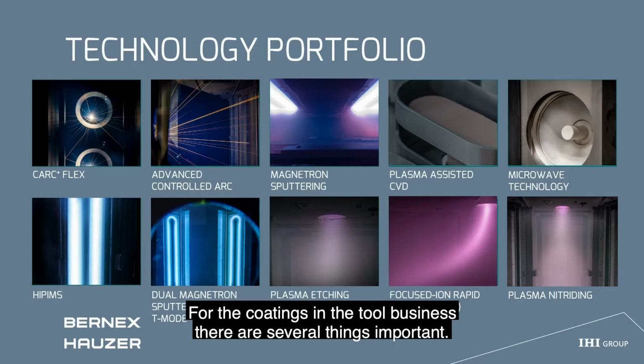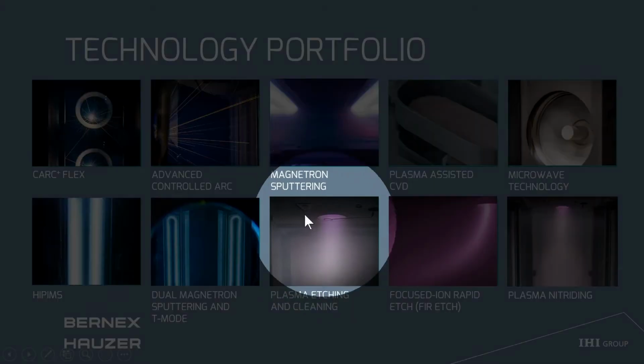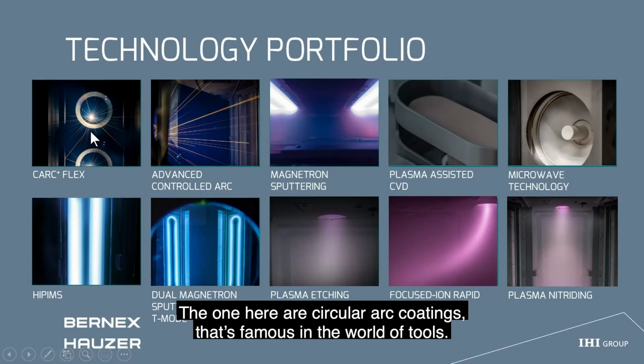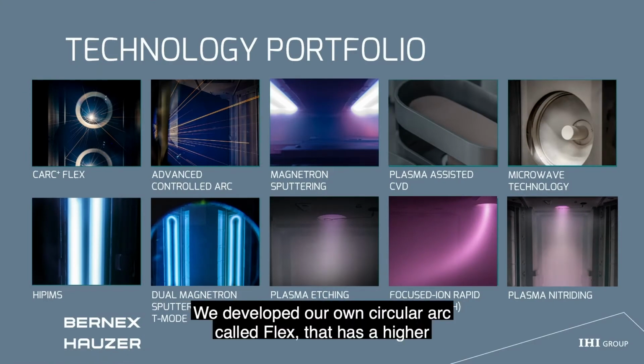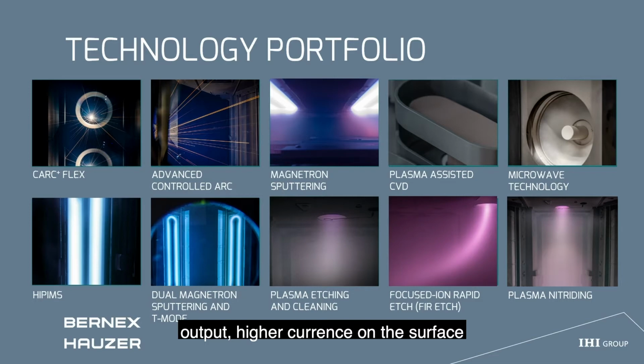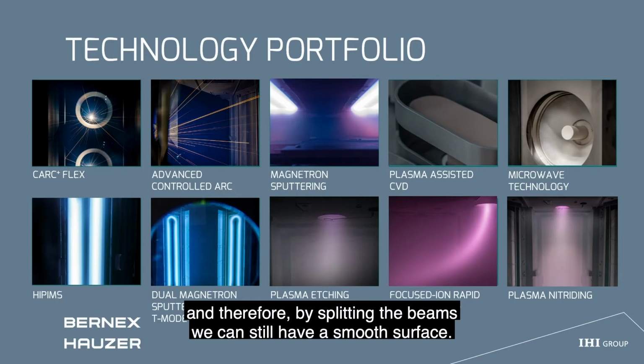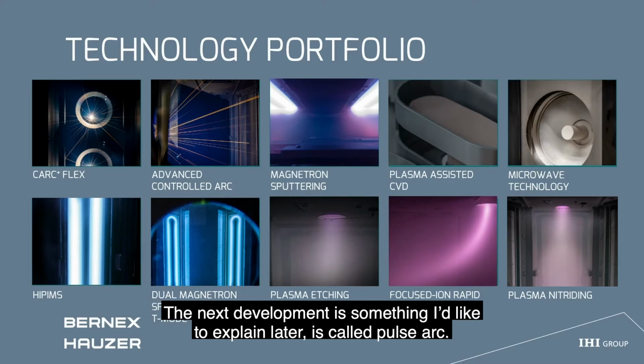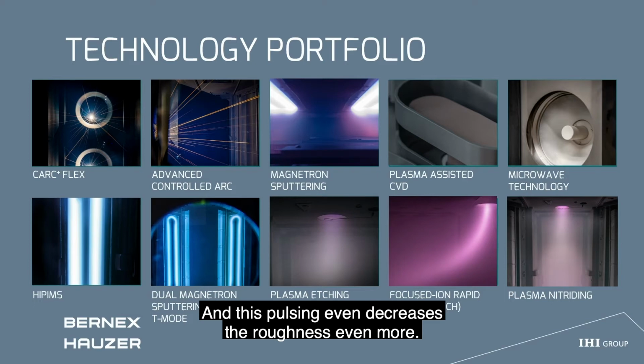For the coatings in the tool business, there are several things which are important. The one here is circular arc coatings. That's famous in the world of the tools. We developed our own circular arc called Flex. So we have higher output, higher currents on the surface, and therefore with splitting the beams we can still have a smooth surface. So the next development in this case is something I will address later on as well. It's called pulsed arc, and this pulsing even decreases the roughness even more.